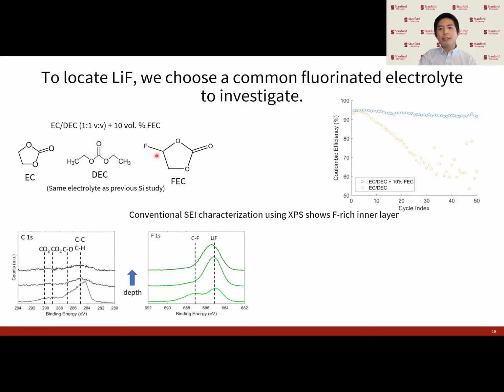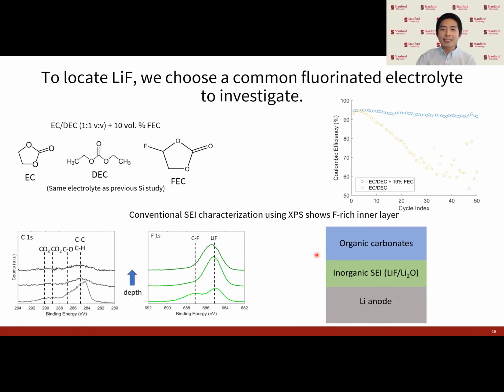If we then carry out this sort of conventional XPS depth profiling of the SEI on the lithium metal in this electrolyte, we can see that there's an outer surface that's rich in organic materials, and then an inner surface that's rich in lithium fluorides and other inorganic materials. And this results in this kind of classic SEI model where we have this bilayer structure of this inorganic lithium fluoride and lithium oxide rich inner SEI layer with a more organic outer SEI layer.